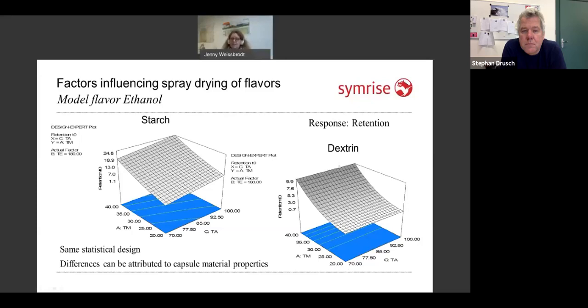So just put in as much as you can of your carrier material. If you don't have a dense surface film, and this dextrin is not surface active, it will not build a surface film on the drying droplet to keep your ethanol inside during your drying process. Just a high solid content will help in this case.